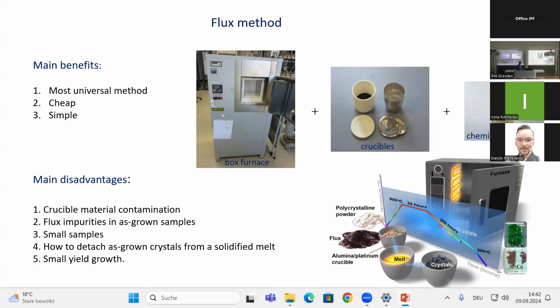So what you need for high-TC cuprates is a very simple box furnace, up to 10,000 euro, low-cost ceramic crucibles, and low-price chemicals; altogether it might be up to 12,000 euro, and you could start your own flux project. It's simple, cheap, and the most universal growth method, because theoretically you could find a proper solvent for any material. The main disadvantages: first I should mention crystal contamination by crucible material, because your flux has to dissolve your material, and at the same time it might dissolve the crucible material too.